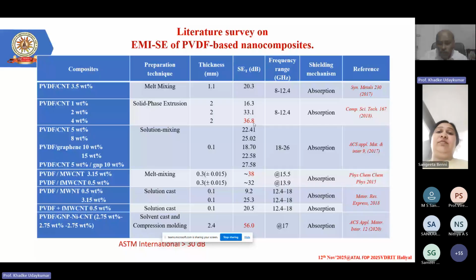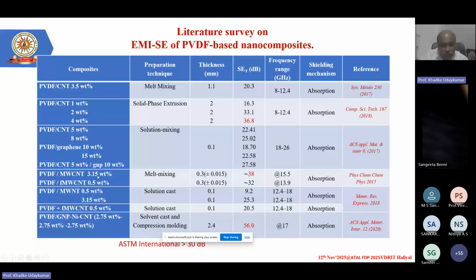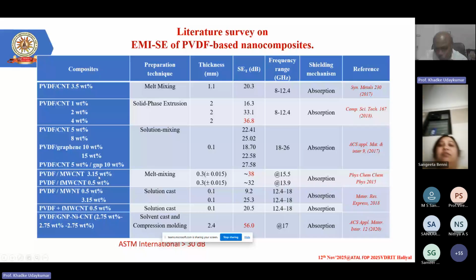In the same way, here also we got values, but since I have not put them as a red mark, because these values are comparatively lesser than this one. Now you see here 38, when I mixed 3.15 percent, and the thickness I made, you got 38. And only one group, which is mentioned in this figure, achieved the highest level of shielding effectiveness, that is 56,